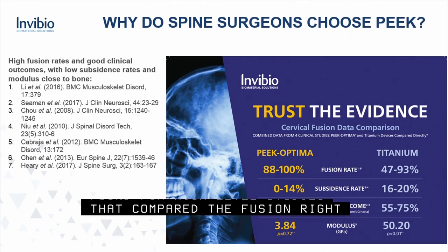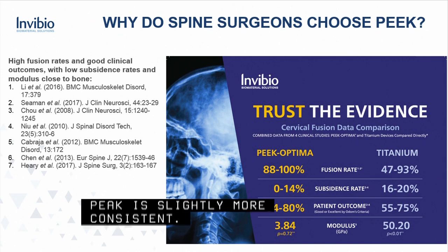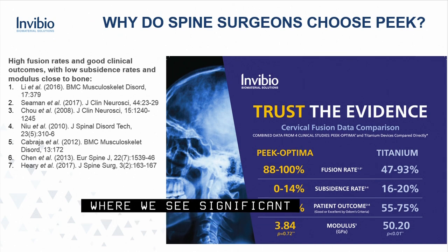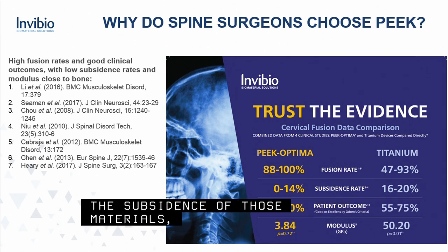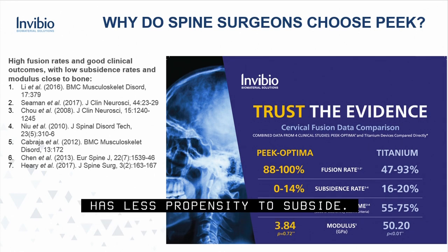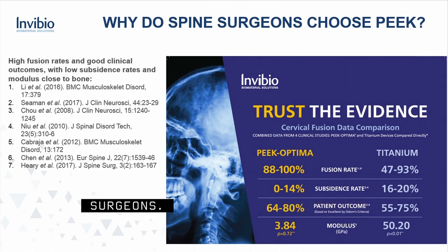Both actually provide pretty good fusion outcomes. PEEK slightly more consistent. But where we do see some significant differences is when we look at the subsidence of those materials into the lower vertebra, where PEEK definitely has less propensity to subside. So despite these good clinical outcomes, surgeons and hospitals are looking for ways to improve upon PEEK materials and titanium materials.